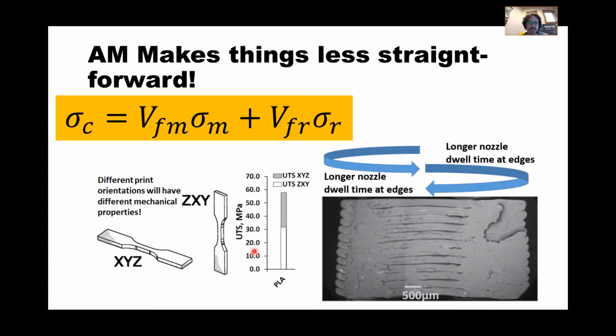Here's a UTS graph for polylactic acid. If I print it vertically in the ZXY direction, it's roughly half of what we got in the XYZ direction. We had some high yield strength values because of the grade of material we were using when we made this graph, so it's a little bit higher than the problem we worked out just now.